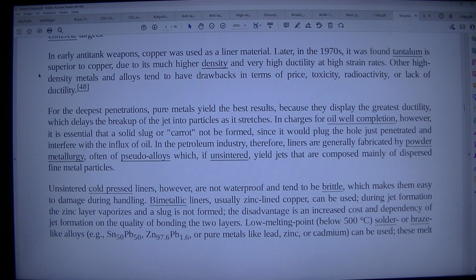48. For the deepest penetrations, pure metals yield the best results, because they display the greatest ductility, which delays the breakup of the jet into particles as it stretches. In charges for oil well completion, however, it is essential that a solid slug or carrot not be formed, since it would plug the hole just penetrated and interfere with the influx of oil. In the petroleum industry, therefore, liners are generally fabricated by powder metallurgy, often of pseudo-alloys which, if unsintered, yield jets that are composed mainly of dispersed fine metal particles.